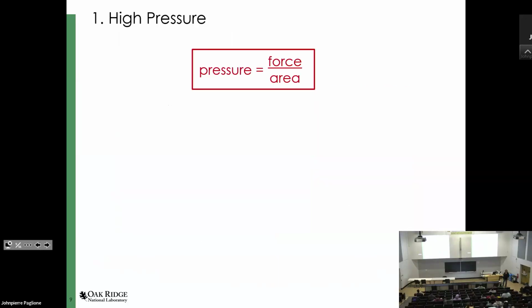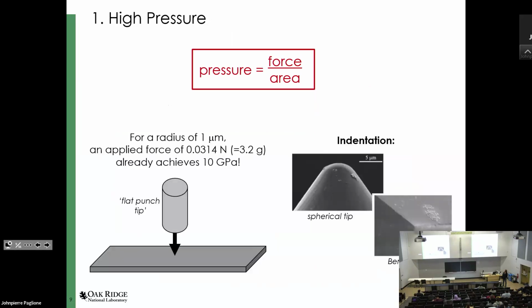So now to switch over to pressure, and this is the only formula I'm using. As you all know, pressure is force over area. So if you think about it, if you use a very small area of, say, a micron diameter radius, you need very, very small load just to get to 10 GPa. So this is actually used in point loading when you do indentation experiments, or also when people use it to induce phase transitions, where you need minuscule loads to get to relatively high pressures.